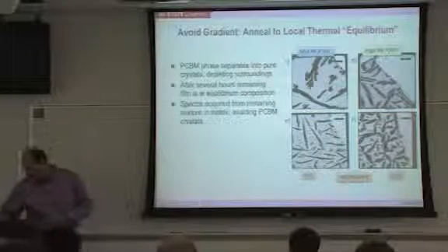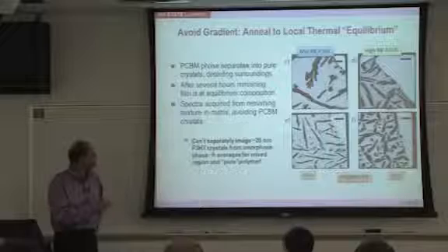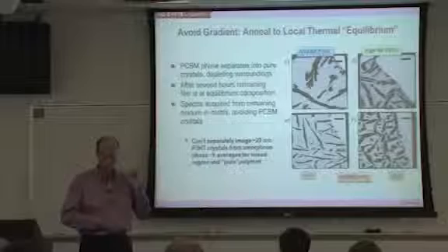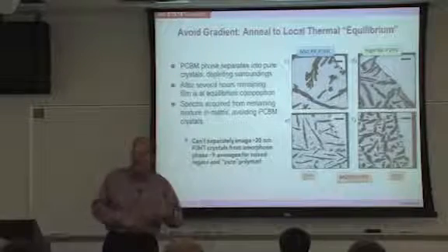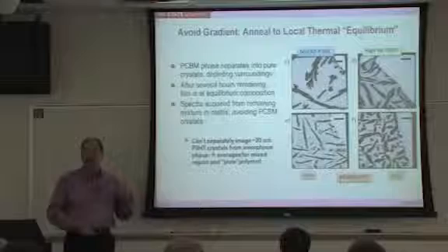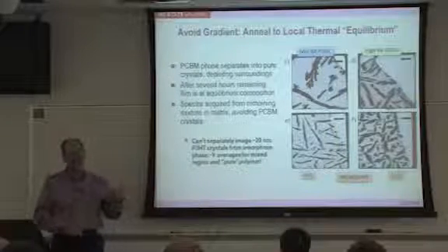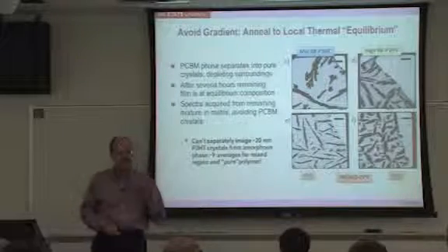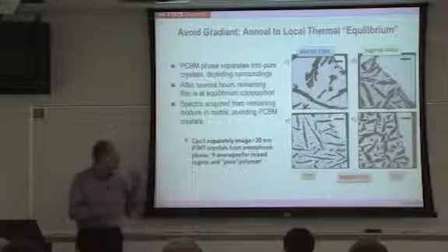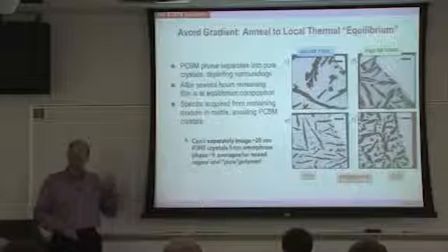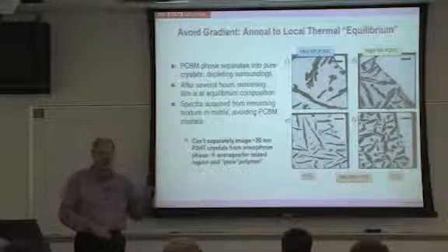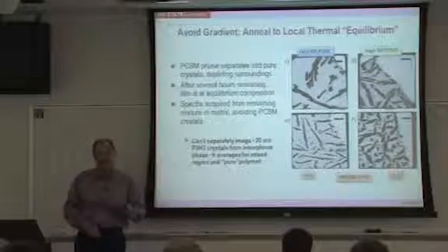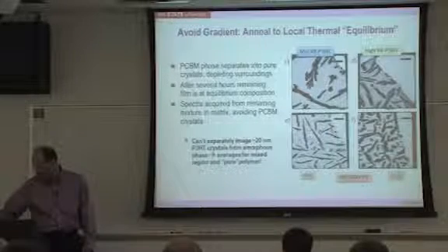So when you do that, though, in P3HT, the problem is that the residual value that we measure isn't directly the value in the amorphous matrix, because the P3HT at that size scale has crystals, and we can't directly see that. We know from wide-angle X-ray scattering that there's no intercalation. So basically, one would need to know the degree of crystallinity to convert our measurement into an absolute measurement of what the miscibility is in the actual amorphous region.